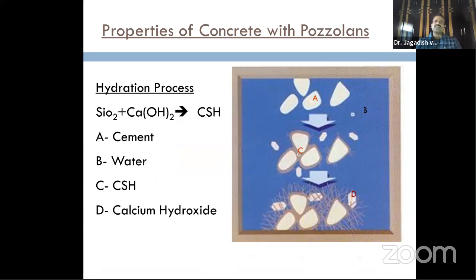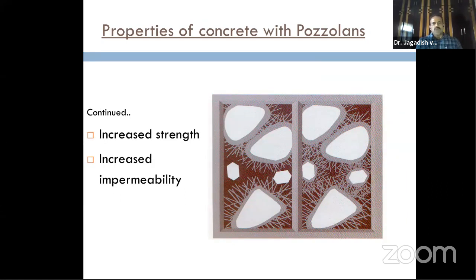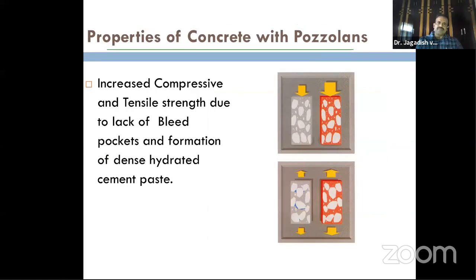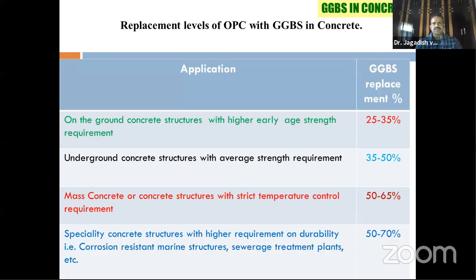But here our interest is GGBS. Anyway, this is the basic reaction. In normal concrete, you have more pores, but here more CSH gels will form. The concrete will become denser. So more dense, more strength, and impermeability increases. Because the bleed pockets are covered with excess CSH gels, forming dense hydrated cement paste, you can definitely observe increased compressive and tensile strengths in the concrete by adding supplementary cementitious materials.